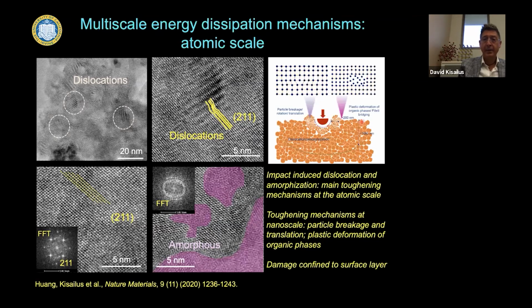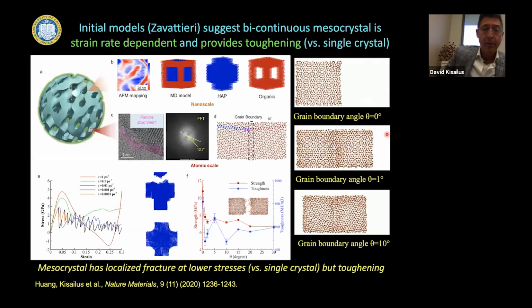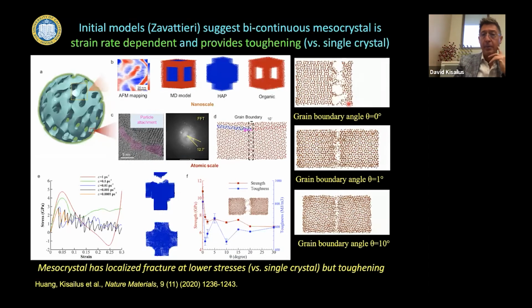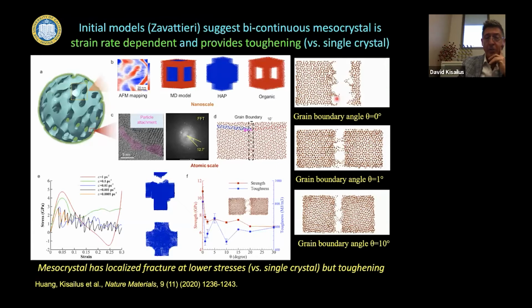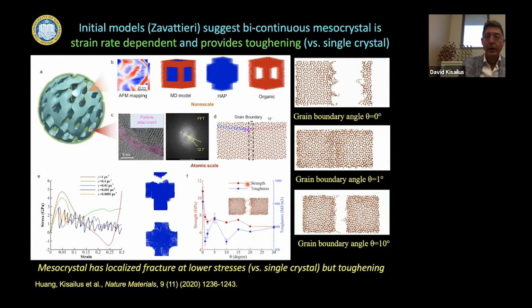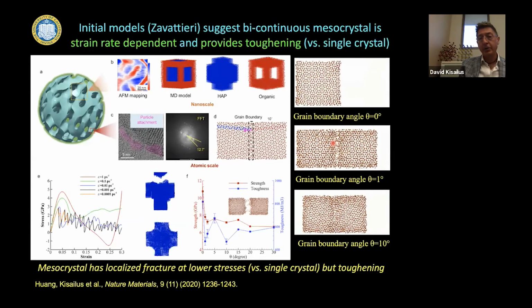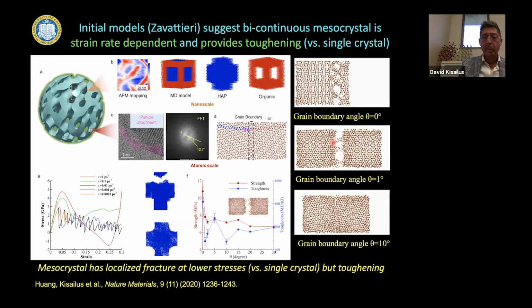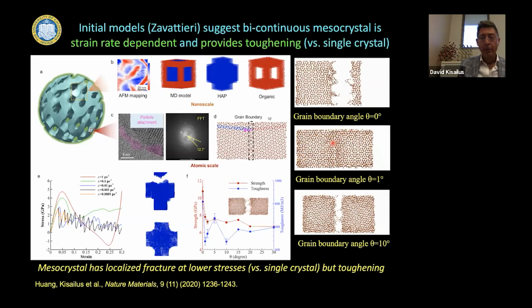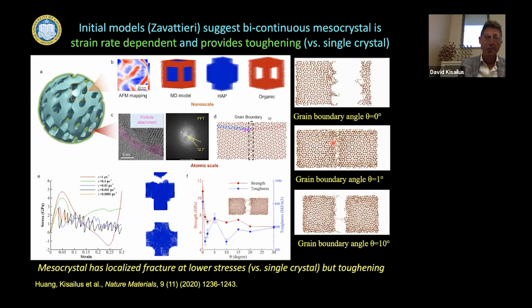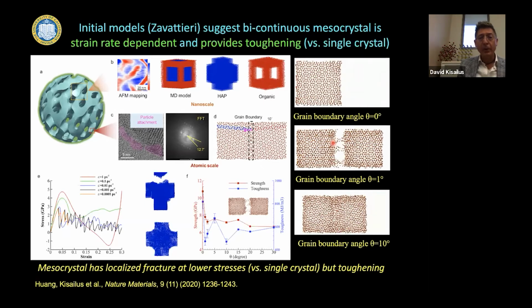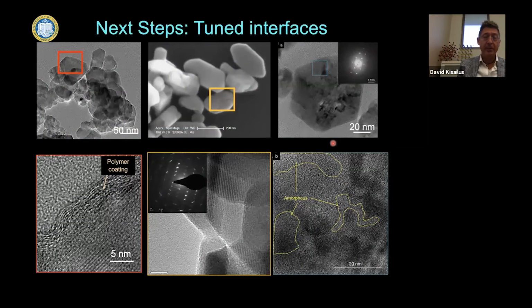And this is something that our collaborator, Pablo, has managed to model. And in fact, what he's shown, for example, on the right side here, is that the energy required to fracture a single crystal is much higher than what you would see trying to fracture something with a low angle grain boundary. So you can actually initiate some of these fractures by having these mesocrystal-like architectures. So what are we going to do with this? Now, this is something that's work in progress. We're synthesizing nanoparticles and then using some organic veneers.